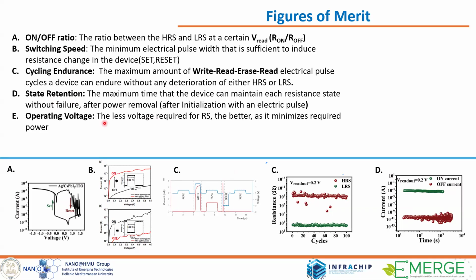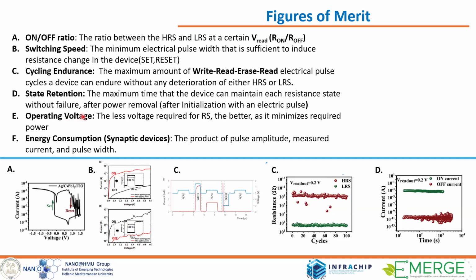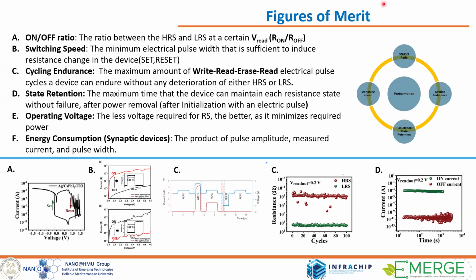Of course, in terms of power consumption, we need to be able to switch between low and high resistance with as low as possible voltage pulses. Okay, so these are the main parameters: on-off ratio, cycling endurance, state retention, and switching speed. And the amplitude of the V set and the V reset is also very important.